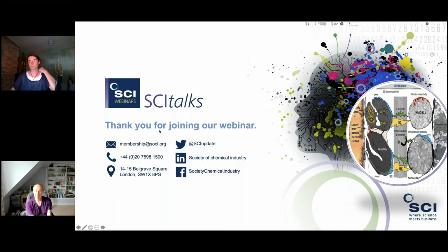Brian, another question? Yeah, so this question is from Marat, who says, does CEI increase the resistance like SEI? Thank you. Yes, well, CEI and the SEI have similar compositions in some respects. Obviously, they're at polar ends of the voltage window. And depending on the anode material in question, SEI can sometimes be a bit thicker and more continuous. But what the CEI will do, of course, is to add interfacial resistance at the cathode particle surface, and this will affect the kinetics of charge transfer. So yes, it can. And if the composition, whether a combination of organic and inorganic phases, impedes ion transfer, then that will significantly affect the resistance internally.